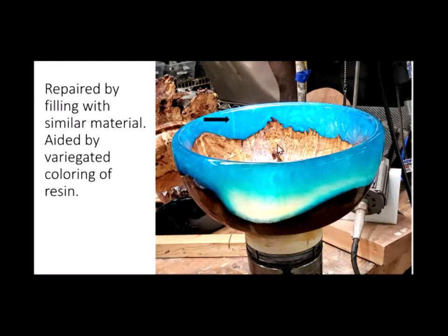But fortunately, because this had a kind of variegated appearance to it, the crack really wasn't all that obvious because it kind of blended in with the other pieces, but it was in 3 of the 4 cores that were in this bowl. So again, that was a lesson learned not to use that resin for a pour that deep. You really need to go with a resin that's meant for a much slower set than that.